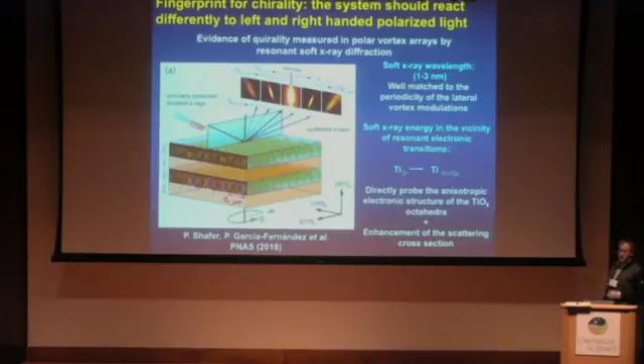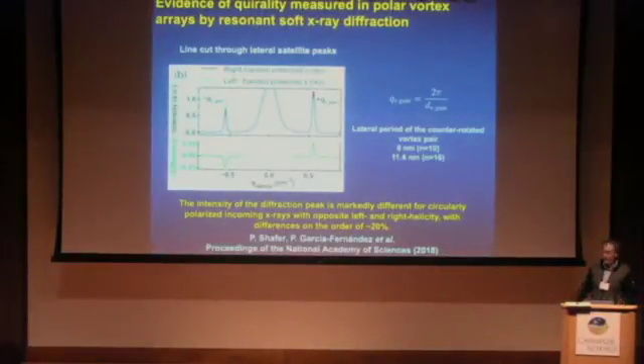So soft X-ray, because of three reasons. First, the wavelength of the soft X-ray is well matched with the periodicity of the vortex, anti-vortex, or clockwise, counterclockwise vortices. The energy of the soft X-ray is very well matched with the resonant transition between the titanium 2p and the titanium 3d. So we can directly probe the anisotropic electronic structure of the titanium-oxygen octahedra, and we enhance the scattering cross-section.